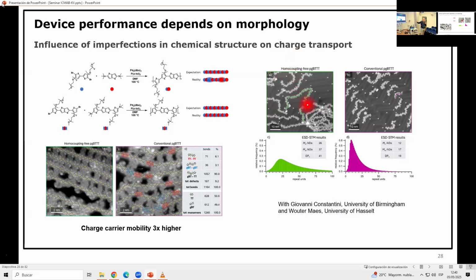And we checked this again with such an STM technique. If in the normal route you have many miscouplings, they can be identified. You can actually see them with STM, where these miscouplings are. And you can actually put numbers on how many defects there are. It can be up to 10%.